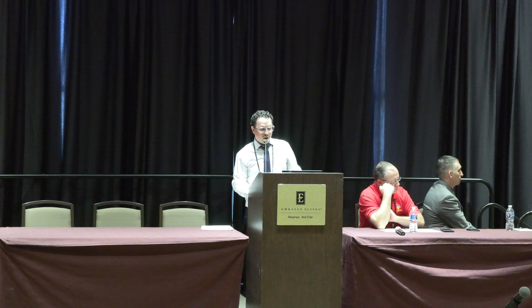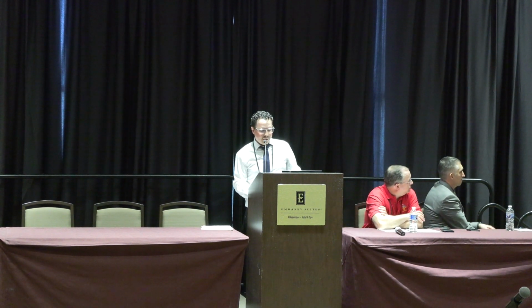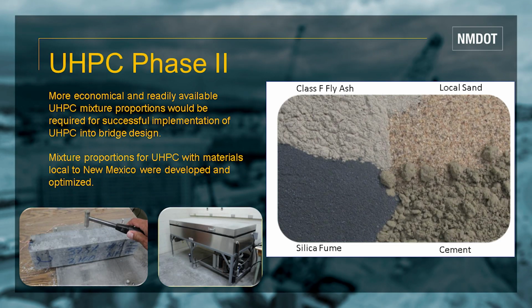Curing practices were also optimized in this phase, and the optimized mixture was resistant to cracking and freezing and thawing cycles. The results demonstrate that UHPC has excellent durability properties. So in this picture is a specimen from the freezing and thawing cycle that held up really well, and also the freezing and thawing chamber. So the materials that were selected were a Class F fly ash, local sand, cement, and silica fume.